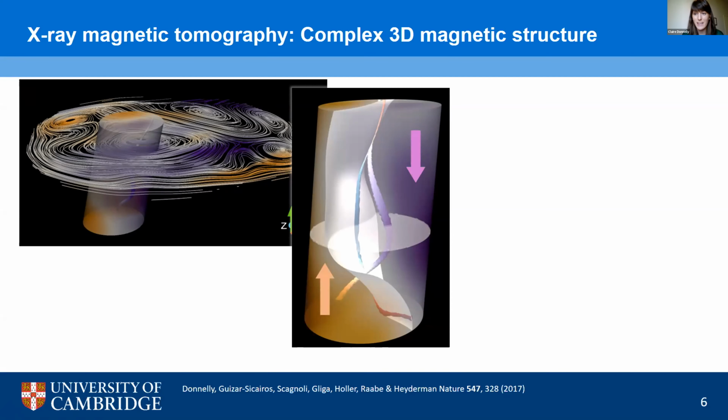Now, what is particularly interesting here is that the core of the vortex, which is represented by this isosurface, actually crosses the domain wall at two different points within this subvolume. And when it crosses the domain wall, the polarization of the vortex actually reverses, as we can see, moving from orange to purple. Now, what this means is actually that the topology of the vortex is changing, and therefore we